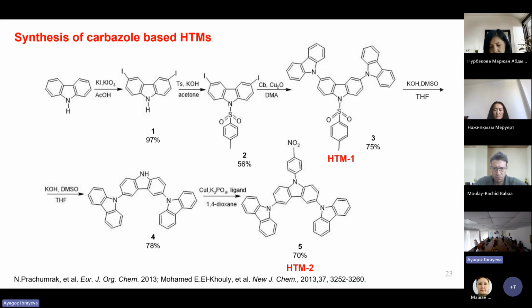After that, we put a protection group, tosyl, on the NH group. Then we further synthesized HTM number 1 through Ullmann cross-coupling using copper catalysis and obtained the product with a 75% yield. After that, we removed the protection group, the tosyl, and obtained a 78% yield. After that, we put nitrobenzene groups in position to extend the electron-withdrawing character and improve this HTM. It is HTM2, with 70%.